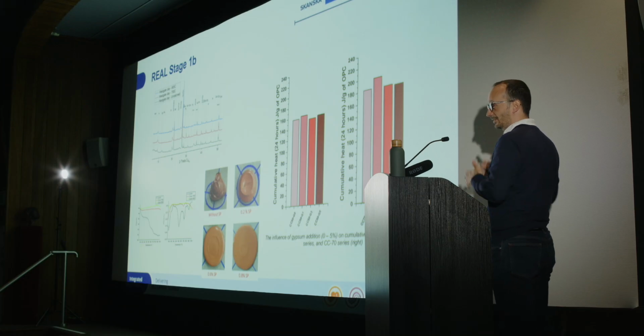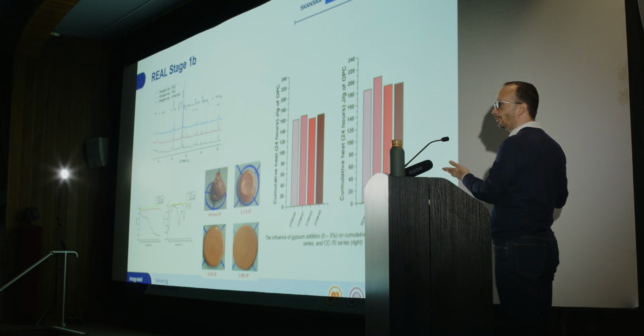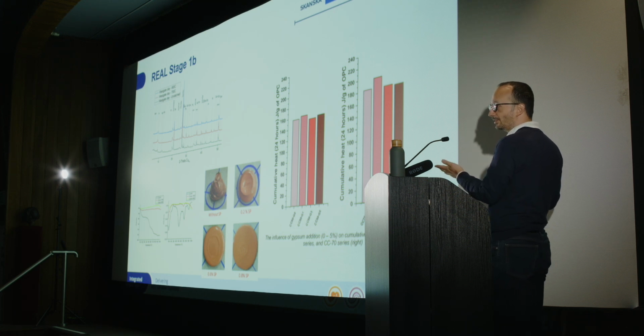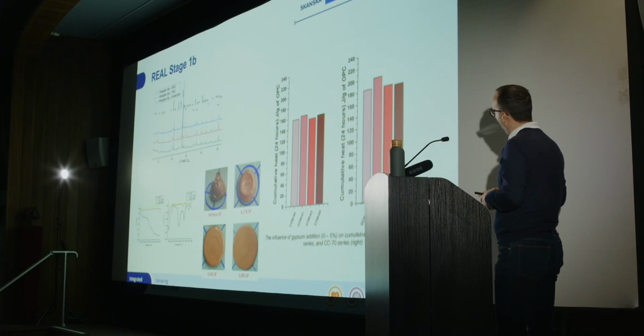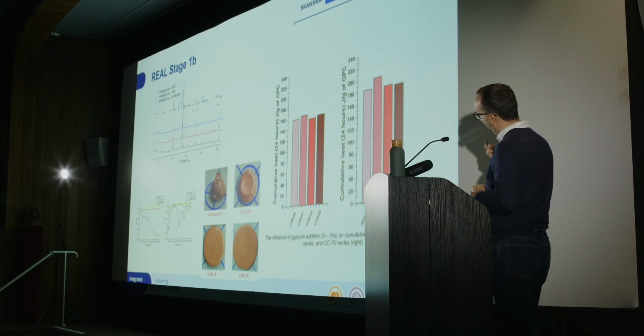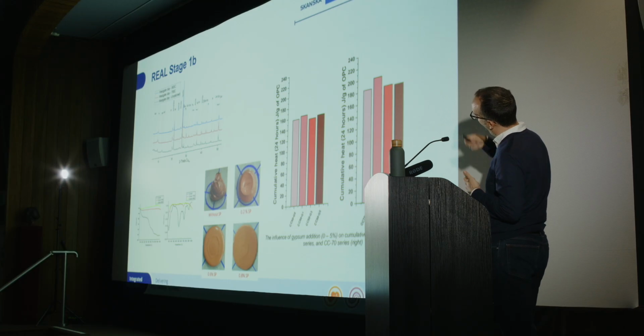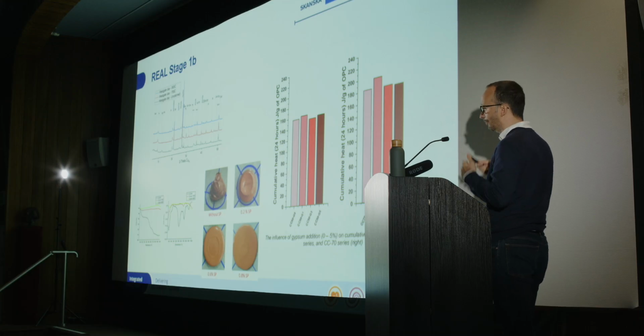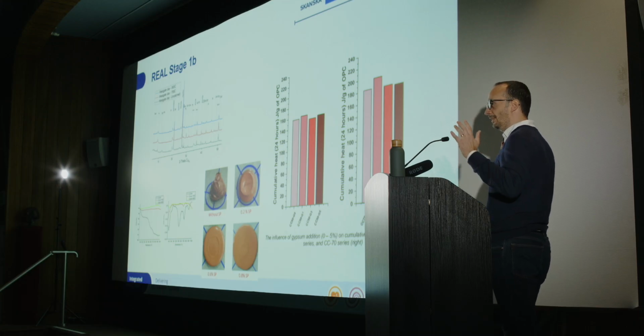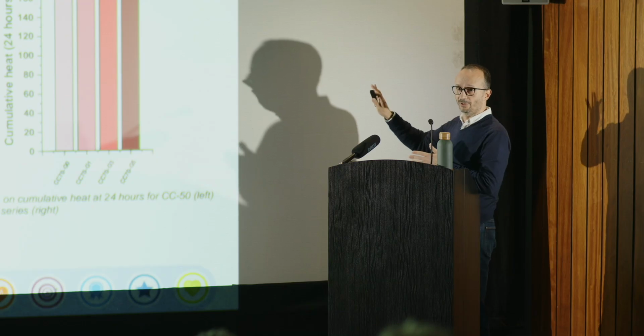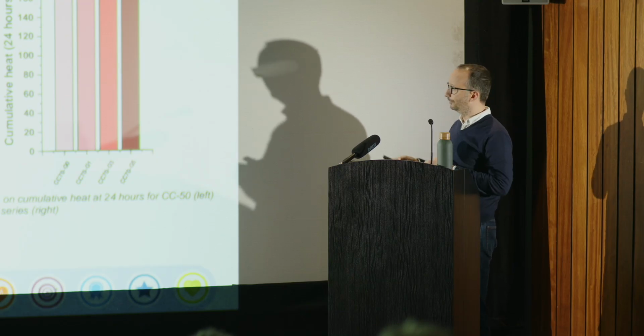The problem we faced straight away, the industry doesn't have admixtures for calcined clays. So we had to start looking into developing admixtures specifically for our clay. And we started looking into whether we can add gypsum to help the clay, to give us more reactivity. We started looking into the mineralogy of the clays, how different they are from the 3 areas. We found that the clays that we tested are very similar, even though not identical, obviously, but they are similar. So that helped us, at least from the concrete and cement perspective, to move on.